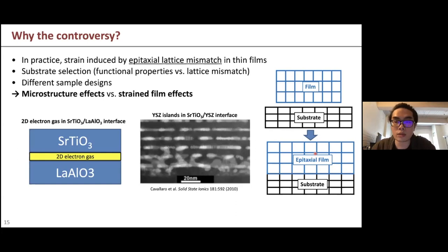And here I'm just showing some examples of what will happen if you don't have a very good selection of the substrate. If you grow strontium titanate on LAO, in between there will be a 2D electron gas. When you're measuring the conductivity of your strontium titanate thin film, I believe the 2D electron gas will definitely affect the absolute value that you measure. And the second thing is, if you have defects, and I'm not talking about point defects, but more like dislocations or grain boundaries or dislocation threads, they can also affect the conductivity measurement that you conduct on the thin film.